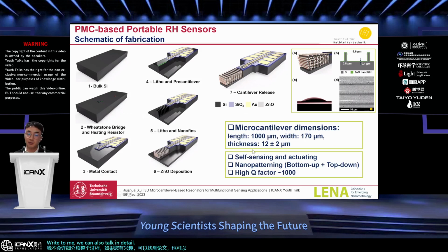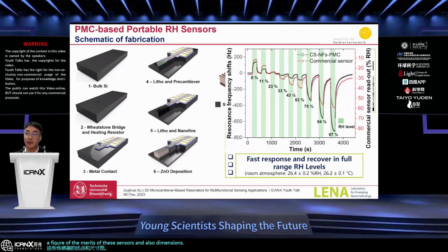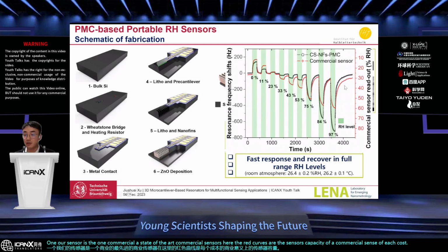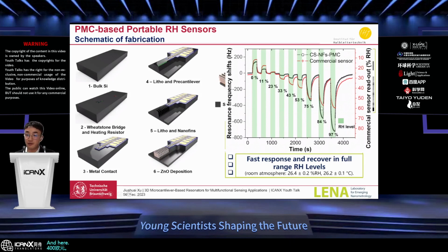Here are some figures of merit of these sensors and also their dimensions. We compared our sensor with a state-of-the-art commercial sensor. Here, the red curve is the commercial capacitive sensor, which costs 400 euros. And you can see clearly our sensor has better performance at the high humidity range, because the high humidity range is always challenging for humidity sensors.